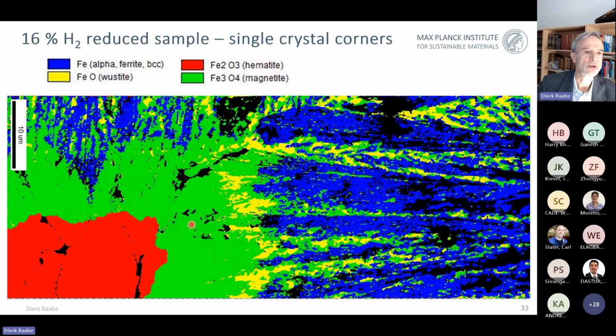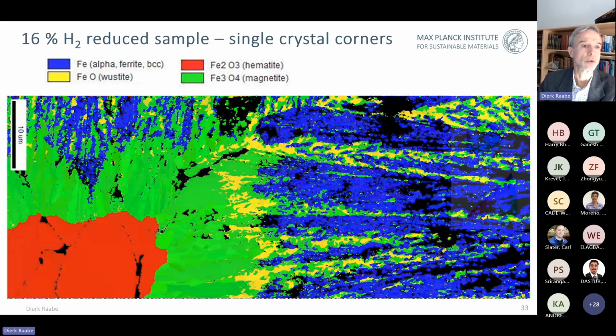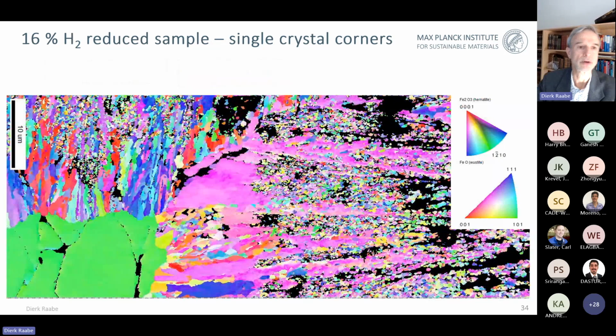But the next steps are already so complex and depend so much on the evolving porosity, the locally heterogeneous nucleation and the stresses, that the further you go down into that redox sequence and transformation sequence, plus all the enormous stresses and defects, this microstructure gets more and more complicated, even though you started from a very clean single crystal. So whatever you start off with, you're ending up in a real mess. And when you look into the texture and the coherency and the crystallography, we are only about to begin understanding what the role of these features for the overall transformation and of course for the mass transport of the oxygen would be.